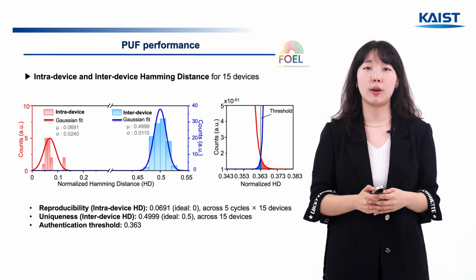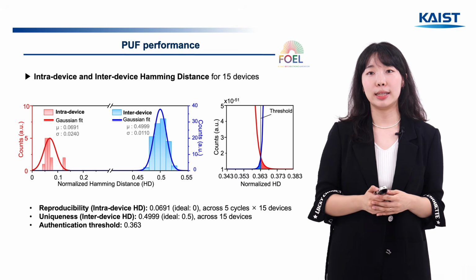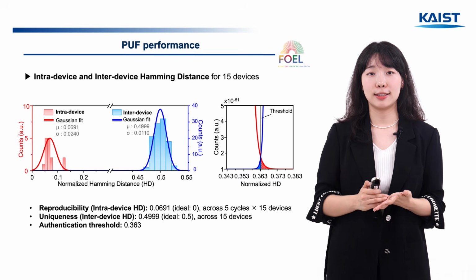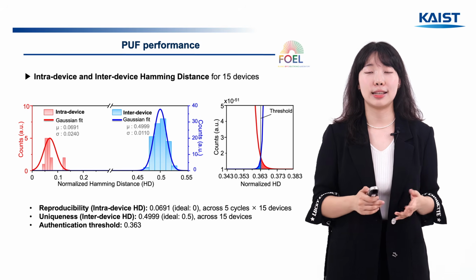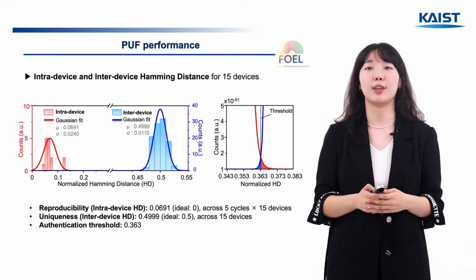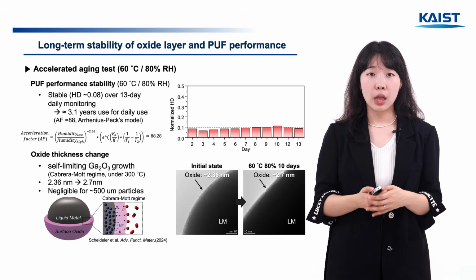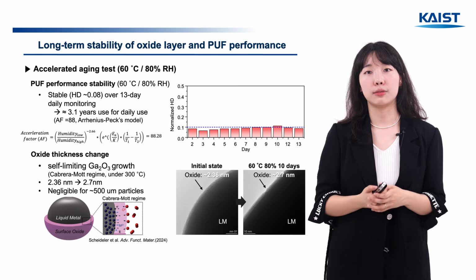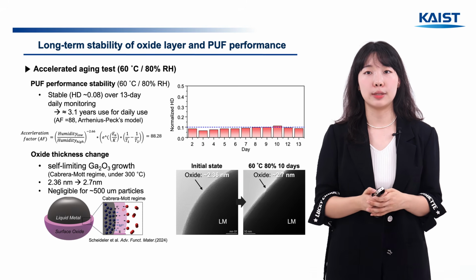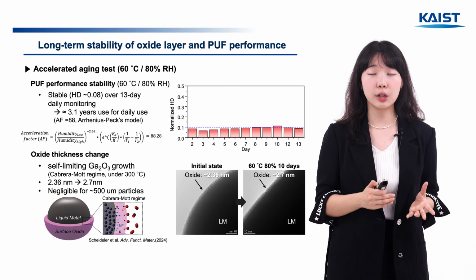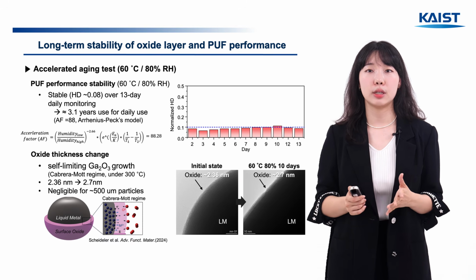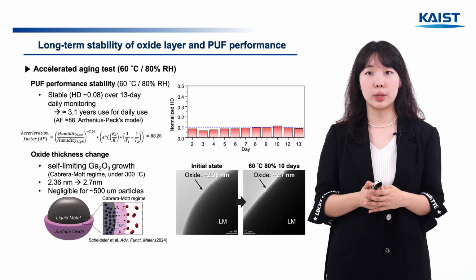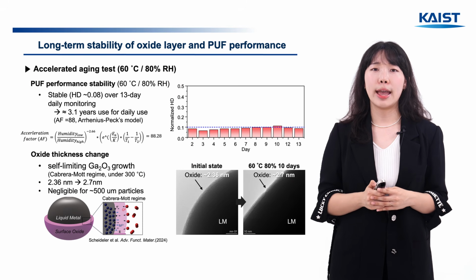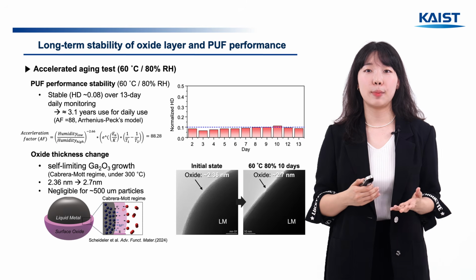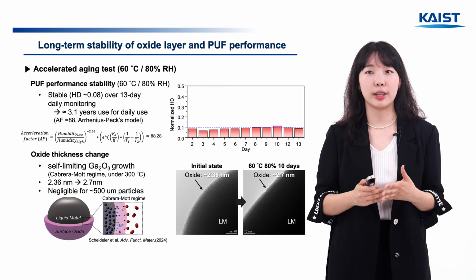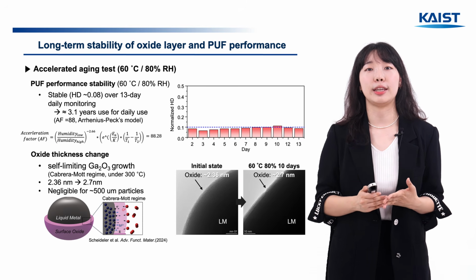To evaluate the PUF performance, we measured the Hamming distance across 15 devices. We confirmed that each PUF has high reproducibility and high uniqueness between PUFs. To evaluate the long-term stability of the PUF, we tested its performance for 13 days in a high temperature, high humidity environment. It maintained stable performance over those 13 days. And using the Peck's model, we can estimate that it can be used reliably for about 3 years of daily use.